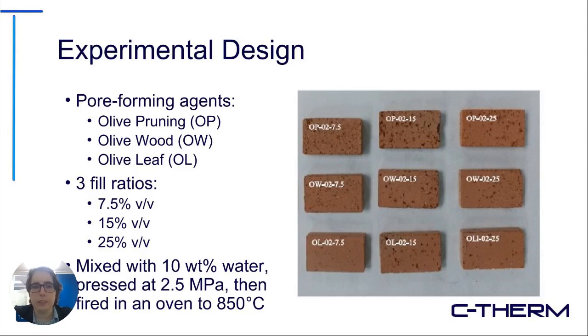After the pore forming agent and the powdered clay were mixed by volume first, 10% of water was added. The resulting mixture was formed into a brick and pressed at 2.5 megapascals of pressure. Then it was fired in an oven up to 850 degrees Celsius, yielding the bricks that you see in the image on the right.